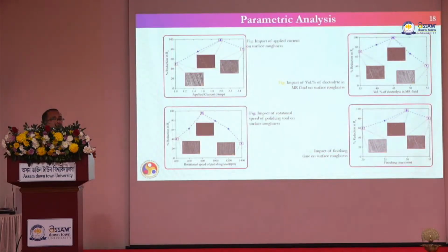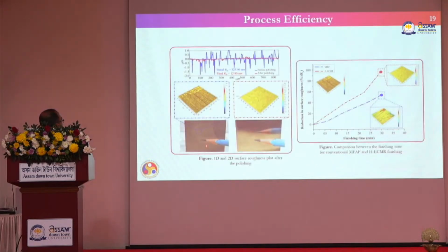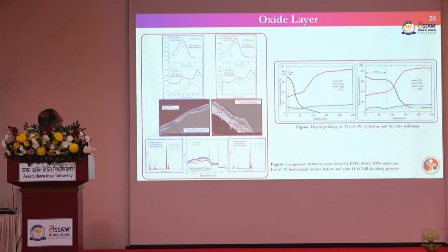After that we did a certain parametric study, by changing the current, percentage of electrolyte, finishing time, and rotational speed, and we got the optimum parameters. Before finishing, you can see that the pencil is not reflected. After that you get this reflective surface. We compared only magnetorheological finishing with the hybrid process. With the hybrid process, we got finishing within 30 minutes, but if you use only magnetorheological finishing, it takes lots of time, 3 to 4 hours. After that we did the XPS study.